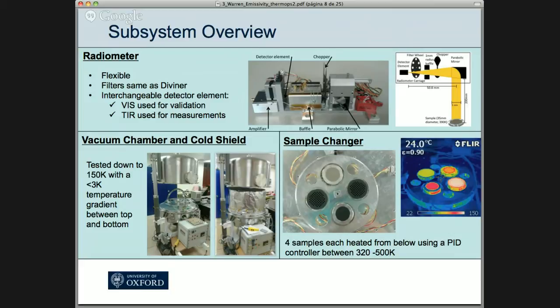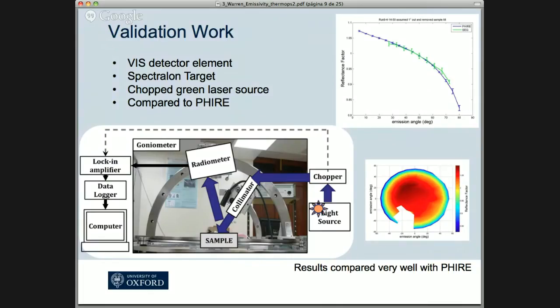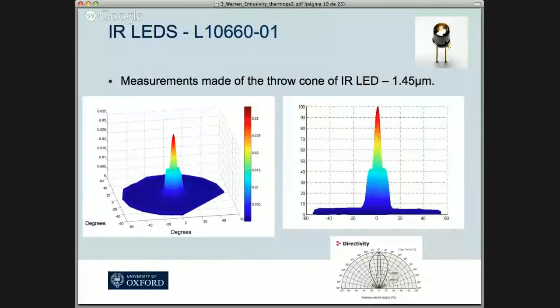I'm going to skip through this quite quickly. We measured a Spectralon target and compared it to a measurement done by a PHIRE goniometer, which is a visible goniometer. And as you can see, the 2 measurements are in good agreement. And then we wanted to do some validation work in the thermal infrared. So we measured a load of infrared LED throw cones, and that worked really well.